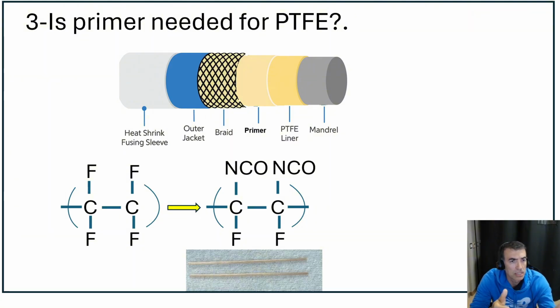So for this example, they are replaced with the diisocyanate functional group that are very reactive. And when the primer is applied, these groups are very reactive and would react with the outer jacket material, nylon or PBAX, and will create a strong bonding between the primer and outer jacket. So it really depends on the bonding that you need. A strong bonding requires application of the primer.